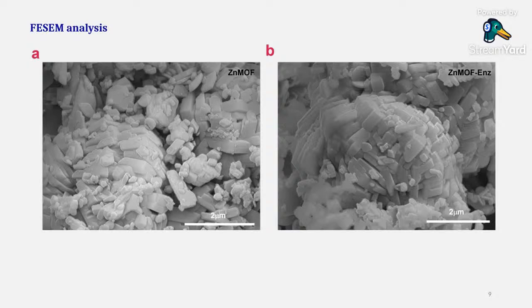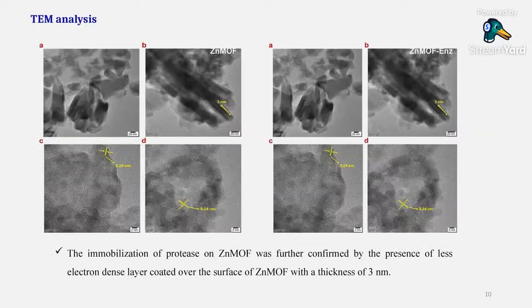After confirming this, we did scanning electron microscopy to see how the surface looks. You can see a rhomboid shape for the zinc MOF. Once you coat the surface, you see almost a similar thing. Here we can't differentiate, but in the transmission electron microscope, you will see the coating of the enzyme giving a little bit darkish color. If you look at the zinc MOF and the enzyme, you can see more of the coating here, the surface with darker colors.